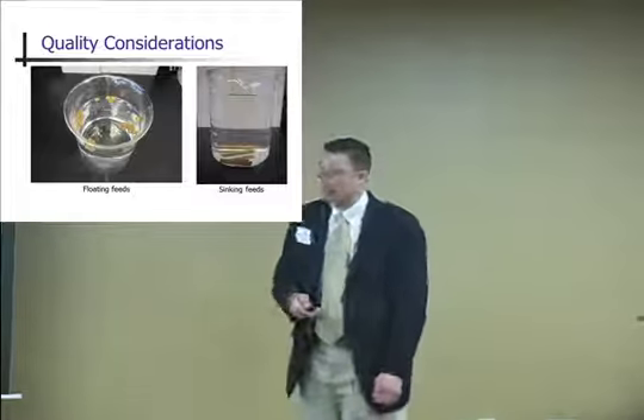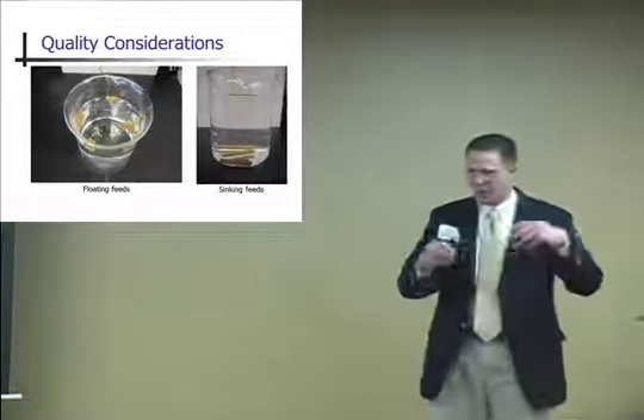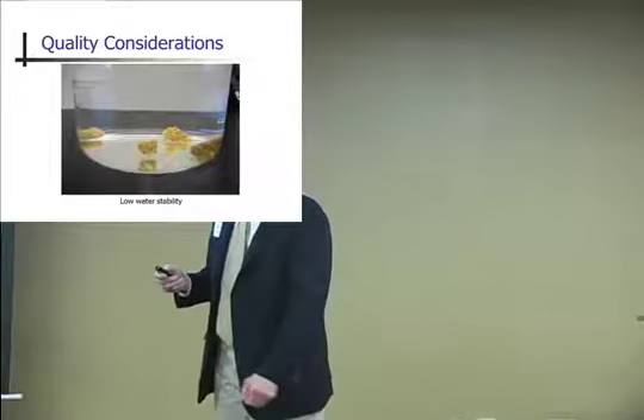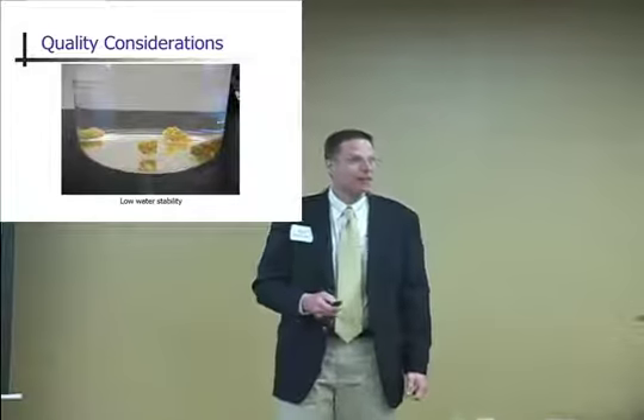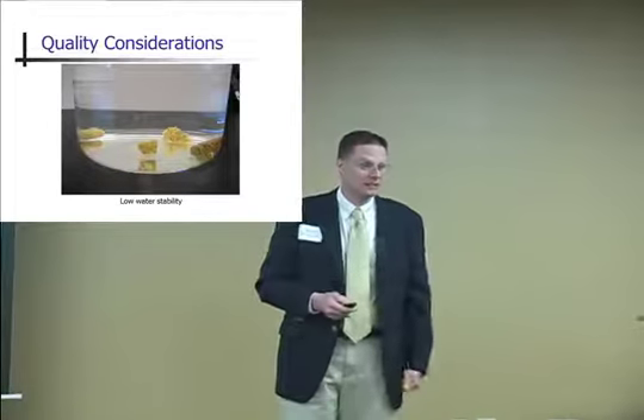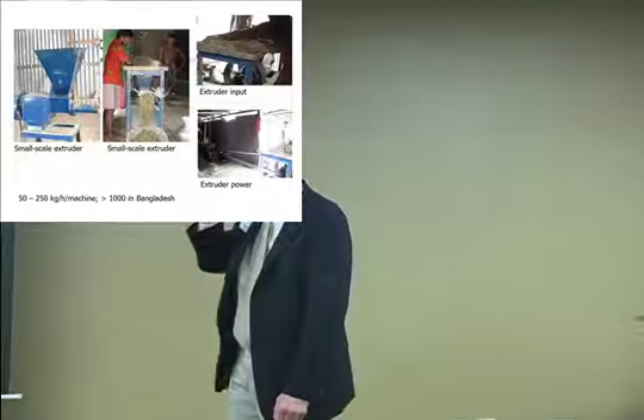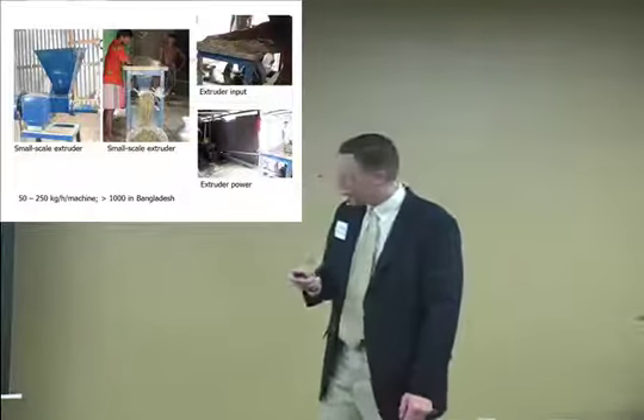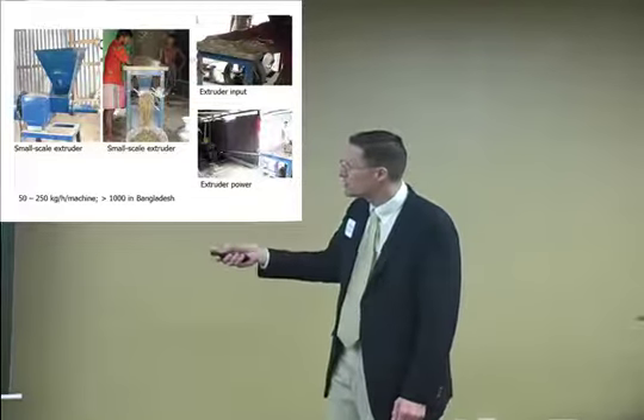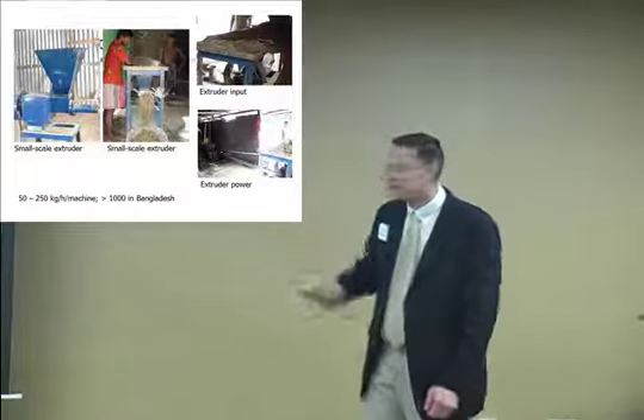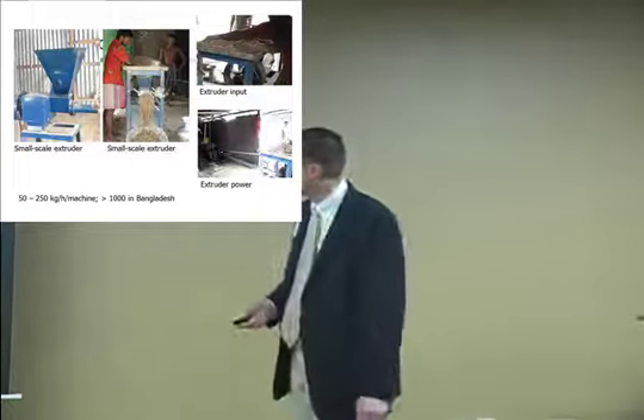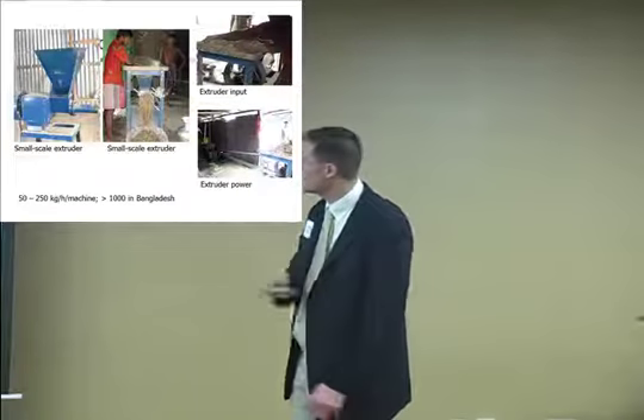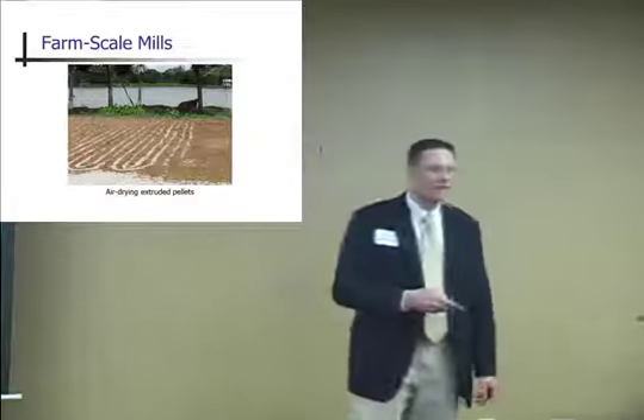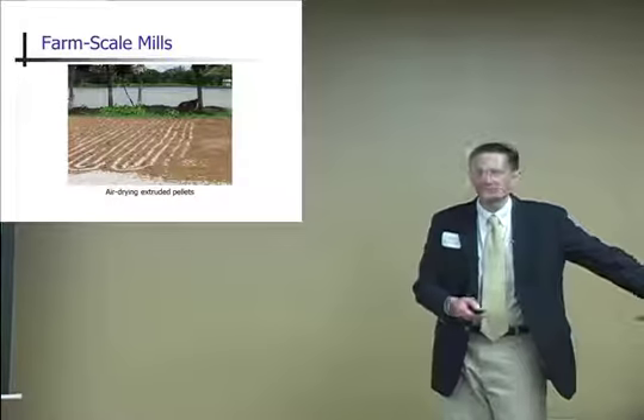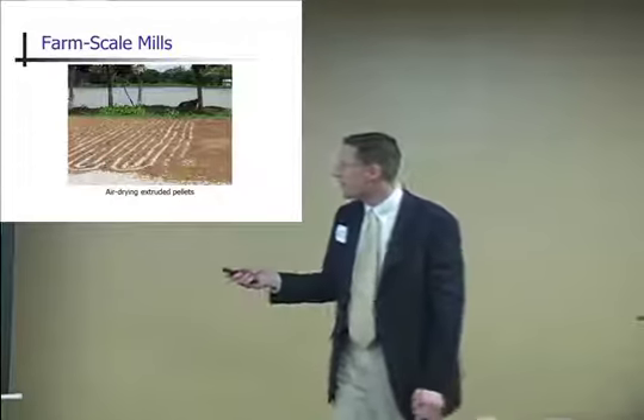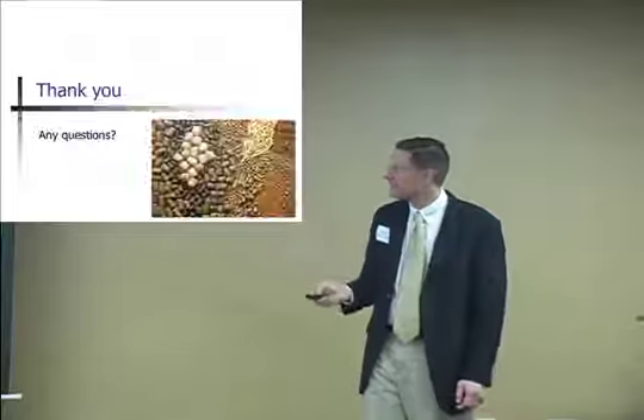So, a little perspective. We talk about making high quality feeds using extrusion. You can make a lot of feed with machines that are not as fancy as we have here in the US. This is an example of some work I'm doing in Bangladesh right now. There are over 1,000 of these small-scale extruders. No temperature control, no water injection, no steam injection. Basically, you blend everything up by hand and dump it in. And then you set it out on a concrete pad to air dry. Now, granted, the pellet quality is more like this than this. So, trade-offs.